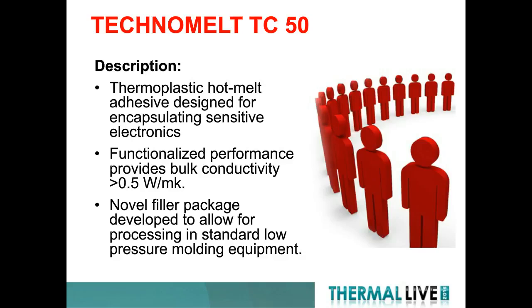We functionalized the performance of the material to provide a bulk conductivity over half a watt per meter-K. These materials, as a resin themselves, are typically 0.2 to 0.3 watts per meter-K, meaning they're effectively insulating. There's no heat transfer through the encapsulant itself. The novel filler package we've developed allows for processing on standard low-pressure molding equipment. In other words, it doesn't require significant change to how the materials are applied today.